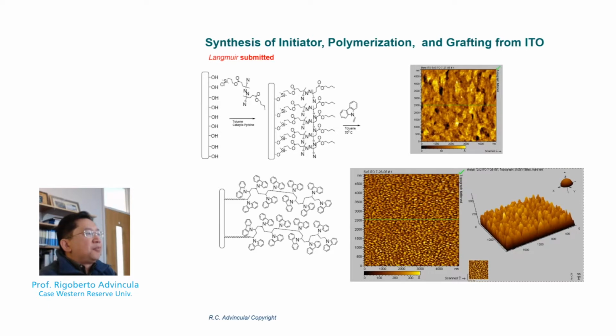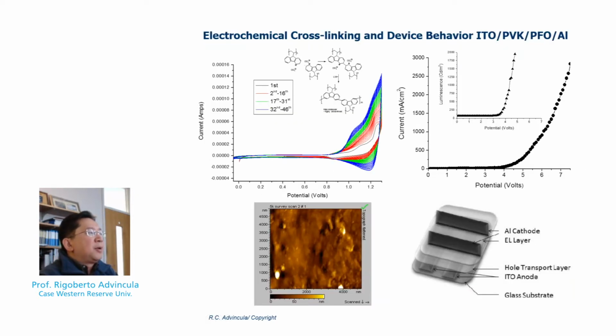In this case, we have a surface, an indium tin oxide, with a rough surface that was modified by polyvinyl carbazole. A polyvinyl carbazole brush, which was polymerized using AIBN initiator and grafted by silane chemistry on ITO, resulted in a homogeneous polymer brush coating on the ITO. Not only did it improve the surface homogeneity, as shown here by the AFM micrograph, it actually improved the device performance.